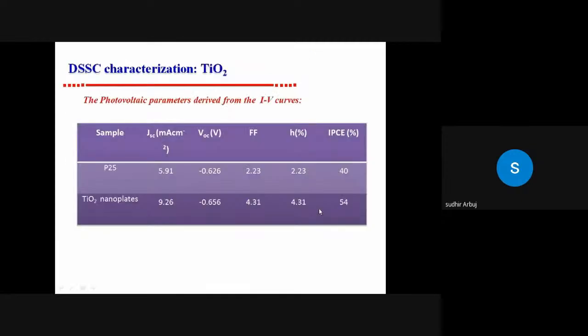Here, the obtained photovoltaic parameters are noted in this table. The maximum power conversion efficiency is 4.31 percent for the prepared TiO2 nanostructure. This is almost double that of the standard TiO2. This maximum is obtained due to the higher current density. Here we got 9.26 milliampere per square centimeter current, which is almost double that of the standard TiO2. This higher current density is due to the formation of nano-sized TiO2 having better particle-to-particle linkage and maximum dye absorption due to nano size.